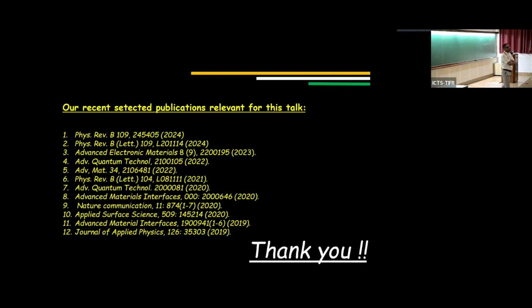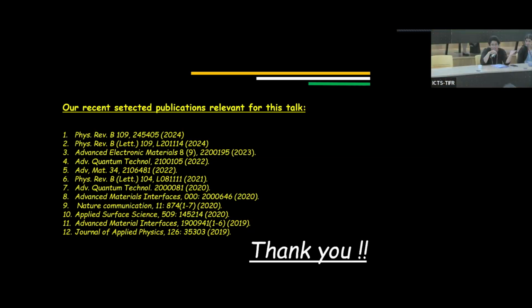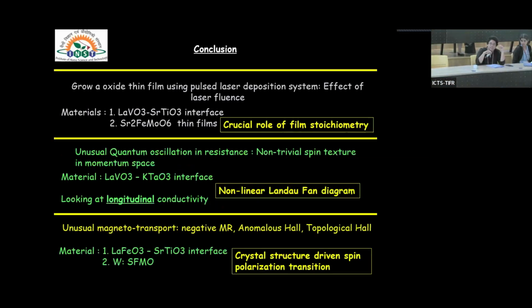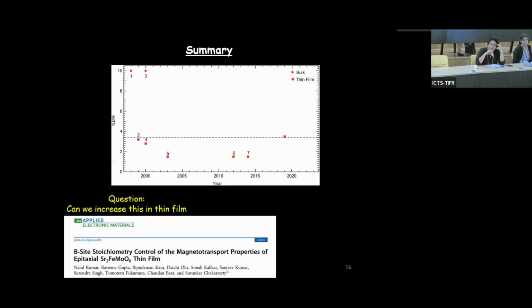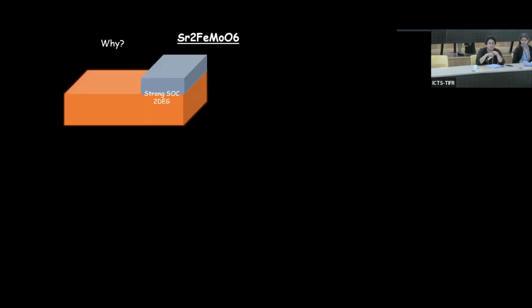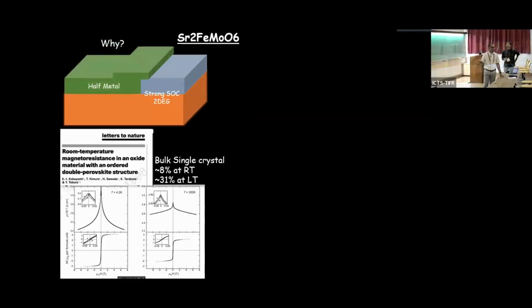Dhavala? Just wondering if you have seen any response to in-plane magnetic field in these samples where you see negative magnetoresistance. The reason being, spin textures can be captured quite a lot by planar Hall effect or so? Yeah, so you're talking about the tungsten doped one. Yeah. Have we measured? Not yet. In plane we have not measured yet, because this sample was prepared 2 months back. So we have not done it yet.